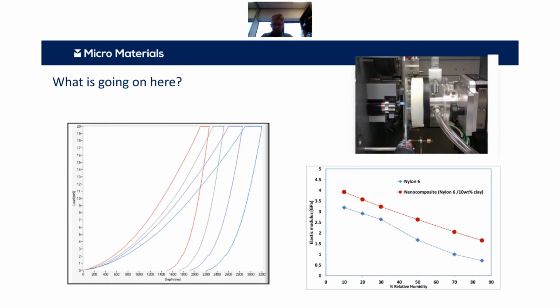Okay, so this works. On the left there are 4 curves again on the thermoplastic, in this case nylon 6, a mechanically homogeneous material, and yet there's quite a difference. What's happening is that the test environment has been changed between those different indents, by using a small volume humidity cell that we have as an option in the nanotest, which one of my colleagues, Adrian, developed. This allows a small volume to be rapidly changed.